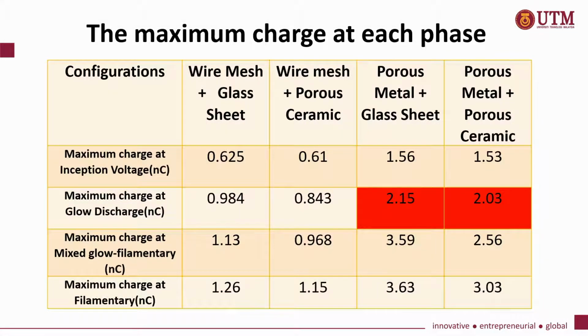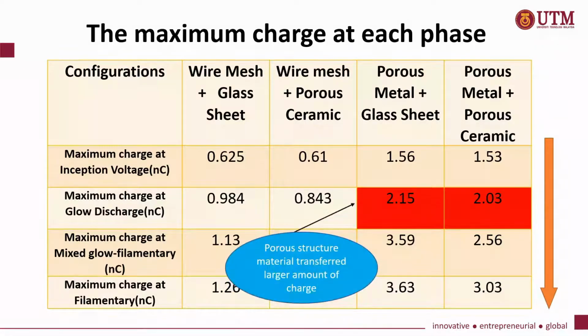Table 2 compares the data on the maximum charge transfer at each phase for each configuration, based on the results obtained from the Lissajous figure. As detailed in Table 2, we can see that the maximum charge transfer gradually increased with the applied voltage from phase to phase, which shows that the amount of charge transfer is directly proportional to the applied voltage. Besides, it was found that the configurations with the porous structure material have a larger value of charge transfer during the discharge compared to other configurations.